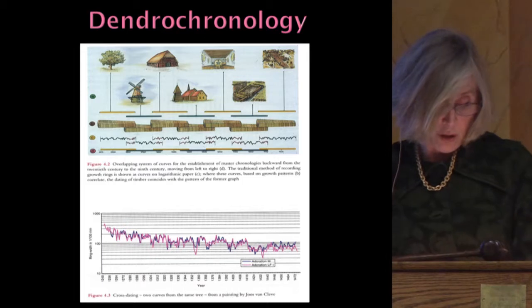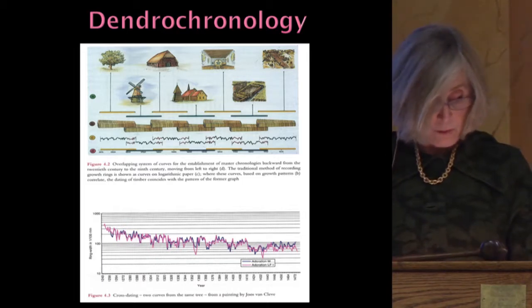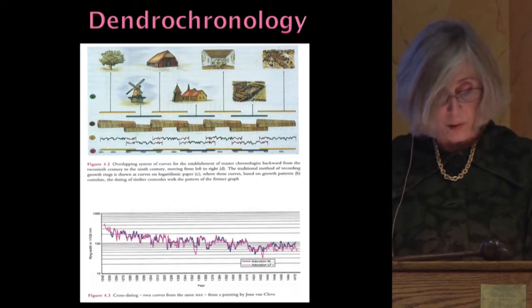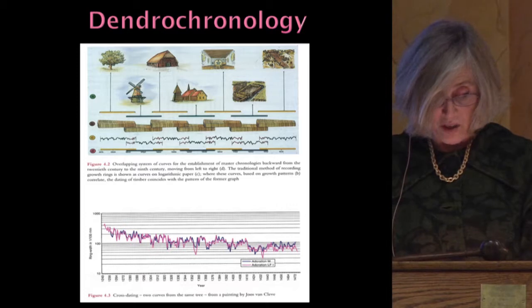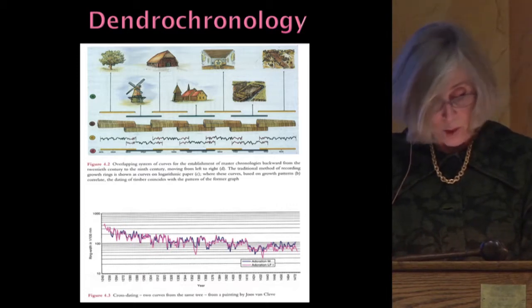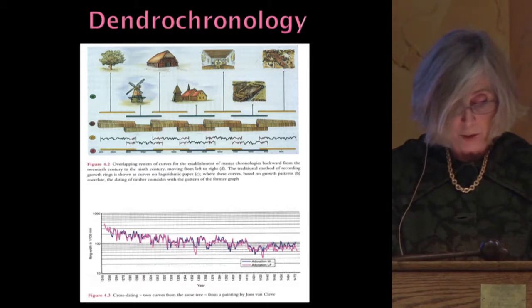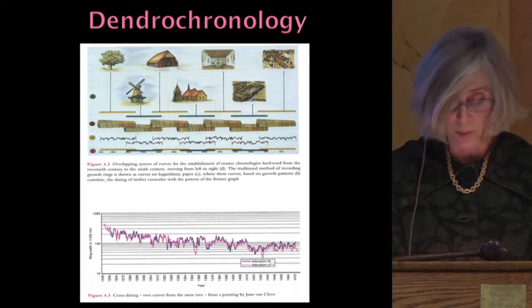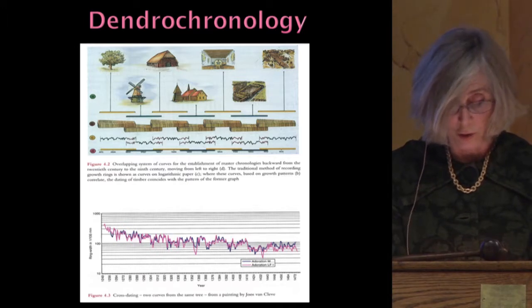The determination of ring widths can be done by looking at the panel edges under magnification, or sometimes by studying X-radiographs of end-grain sections. If dendrochronology indicates the tree was probably felled in 1500, we know that the painting could not have been done before that date, and that it was probably done around 1505 or 1510, allowing for a typical period of wood seasoning. This can be helpful in investigating art historical issues such as authorship.